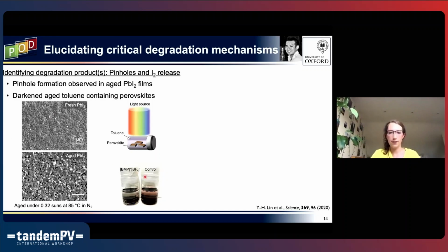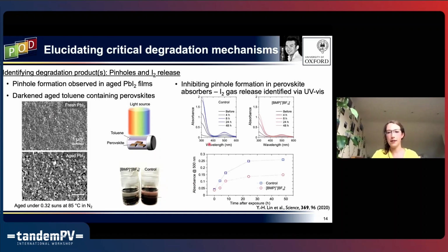And if we look at just even visually these perovskite films in toluene versus the control after light exposure, this one looks very brownish, maybe a little bit purpley, and that's just from the I2 that's being released into the toluene. So we can track this peak at 500, looking at how much I2 gas is released over time. And with this ionic additive added in, we have just much slower and less degradation overall based on this release of the I2.